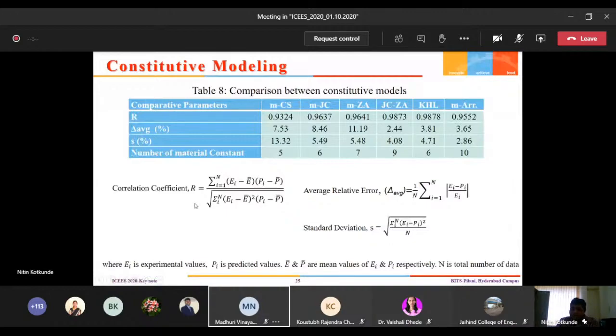Sometimes even though the R value is higher, it can mislead or bias, because we cannot define how much is on the positive side and negative side. Therefore, we also calculate the average error and its standard deviation. So if you see here, the best suitable models are JCZA and KHL, which have a higher correlation coefficient and lower average error. So we have found that for the Inconel 718 material, the JCZA model is best suited, which we can use for numerical analysis and finite element simulation.